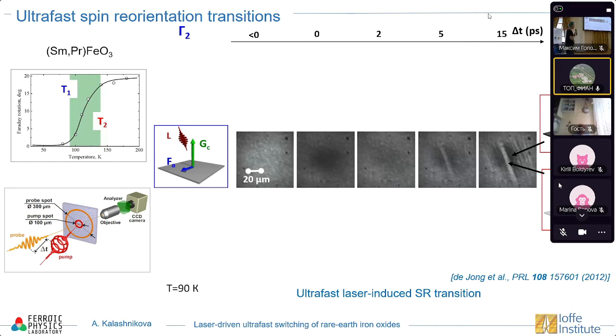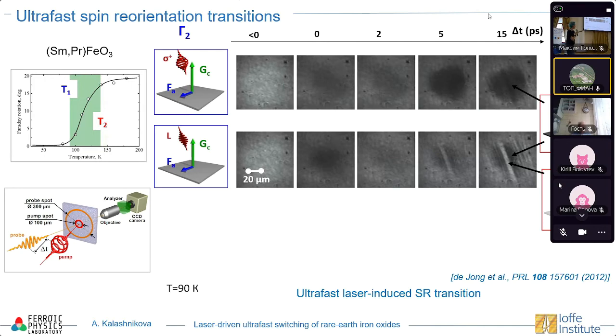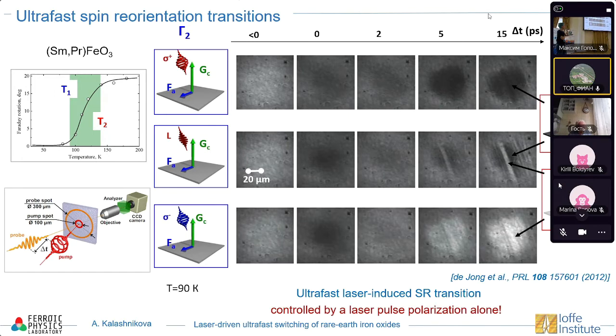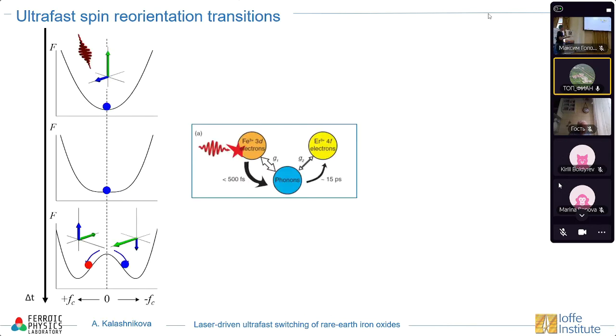But now, if we change the polarization of our pump pulse, if we make it circular polarized, then we see that only the black domain emerges. So we have switching from this phase to this phase. And if we change the circular polarization, then we have switching to the other domain. So basically, we have ultrafast laser-induced spin orientation transition induced by a single femtosecond laser pulse and controlled by the polarization of this pulse. So what's going on?